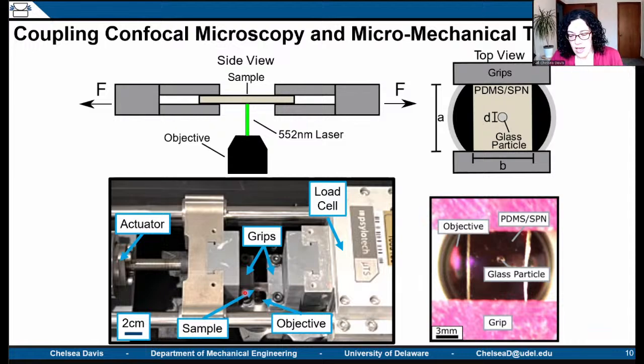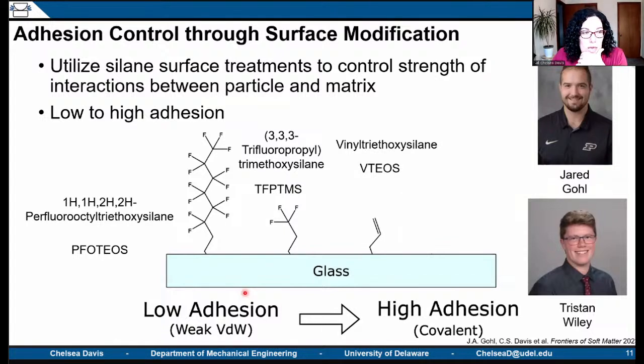So there was quite a bit of materials characterization and process refinement leading up to being able to do this. And after Mitch graduated, another graduate student in my lab, Jared Gohl, came in and really helped us with the chemistry to refine and control the interface between our particle and matrix. So as I said at the beginning, what we care about is composite interfaces. So what Jared did with his undergrad research assistant, Tristan Wiley, is they functionalized the glass particle before embedding it into our mechanophore functionalized silicone with either a long perfluorinated silane, a short perfluorinated silane, or a vinyl termination.